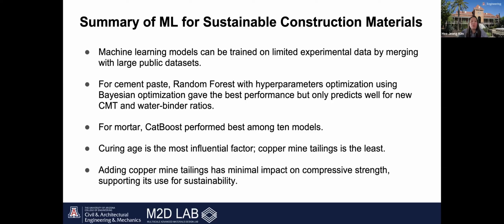In study 1, where we predicted the compressive strength of the cement paste, the random forest model with Bayesian hyperparameter optimization performed the best. However, this model was most effective only for predicting new replacement levels of copper mine tailings and water to binder ratios, not for new curing ages. In study number 2, which focused on mortar, CatBoost was the best machine learning model. Across both studies, curing age was the most influential factor, while copper mine tailings had the least influence on compressive strength. This means that a larger amount of copper mine tailings can be safely incorporated to create more sustainable construction materials without significantly reducing the strength.